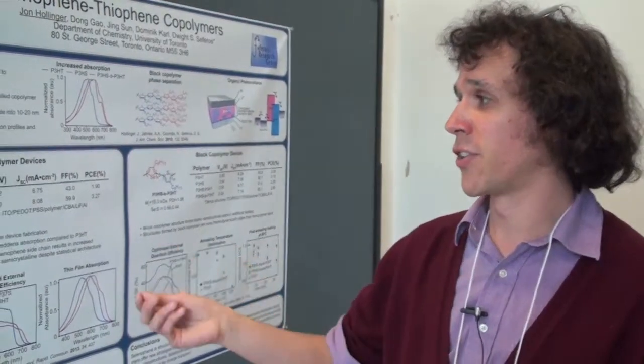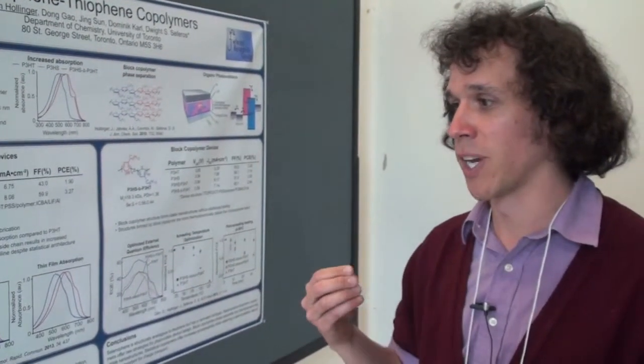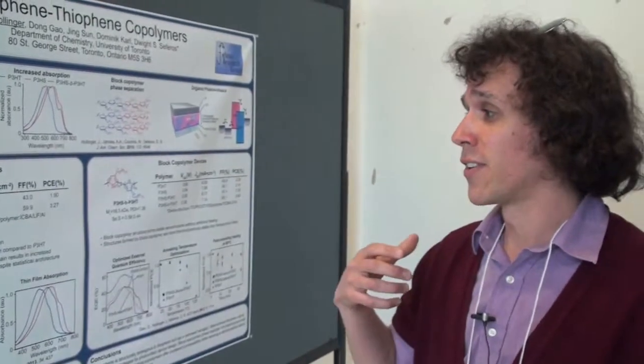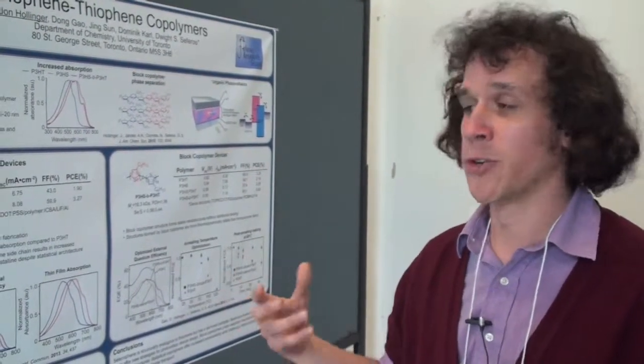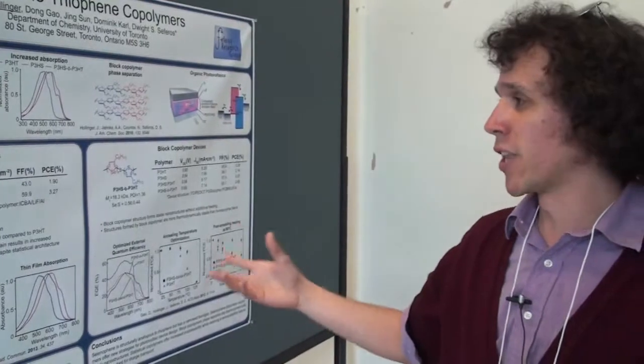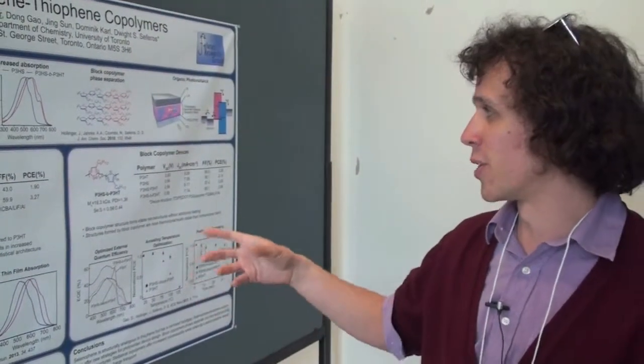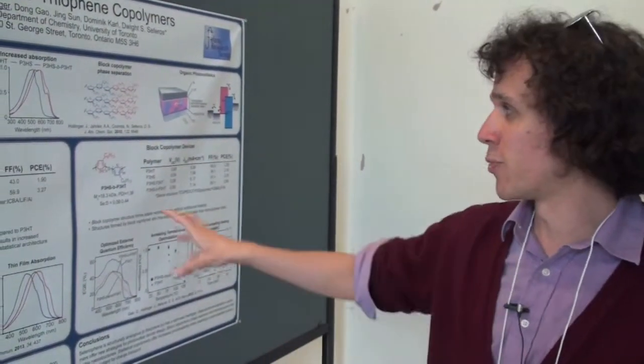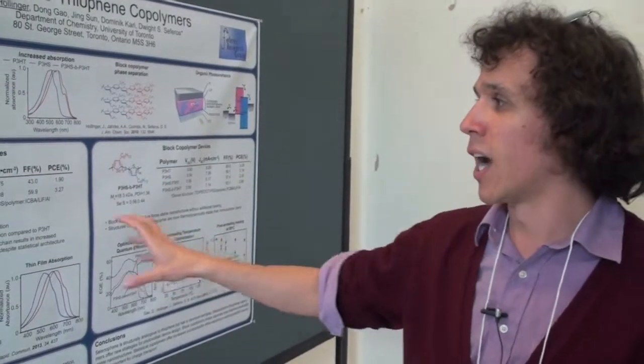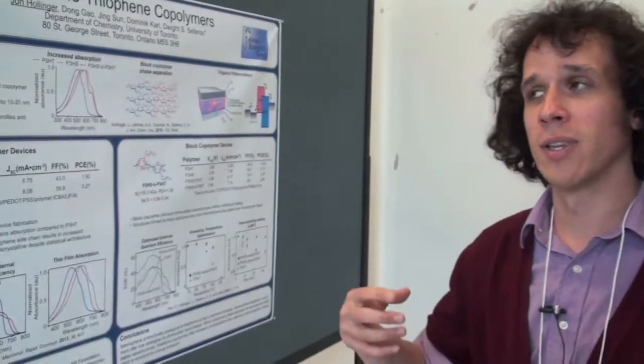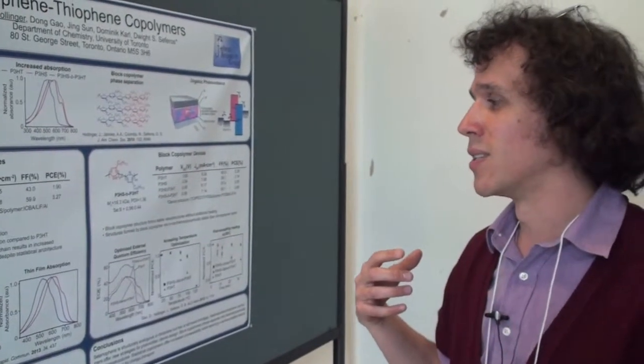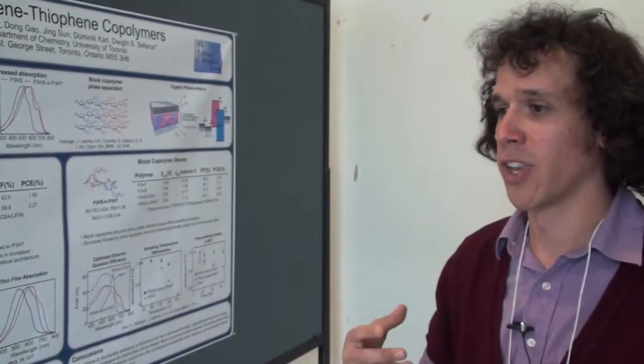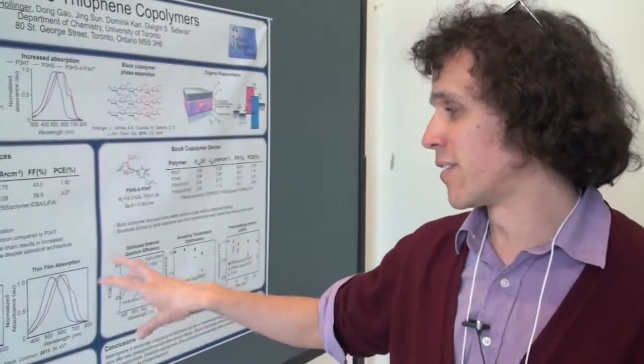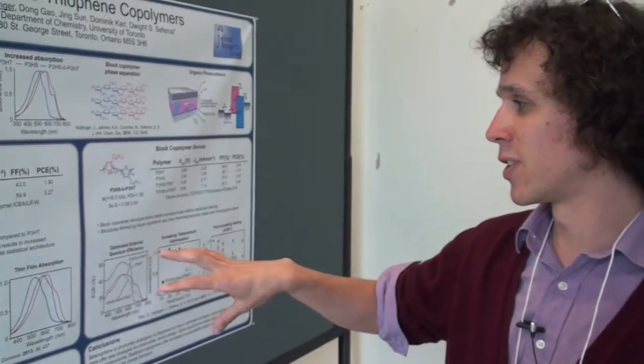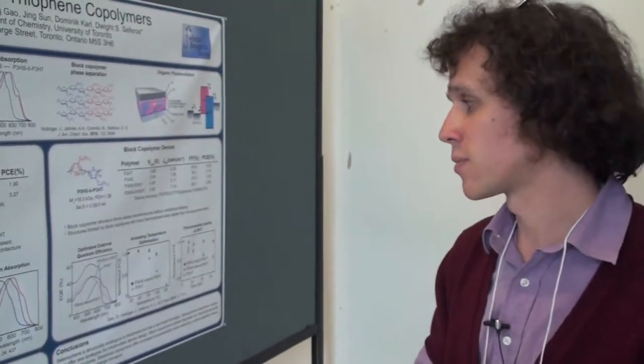But the statistical nature of the polymer does make it much more soluble and thus a lot easier to work with. The block copolymer, polythiophene, isn't the most soluble polymer in the world, and polyselenophene is actually worse. So these polymers are not the easiest to work with. The statistical copolymer really makes the device fabrication process a lot easier to do, while still maintaining the relative redshift in the absorption profile.